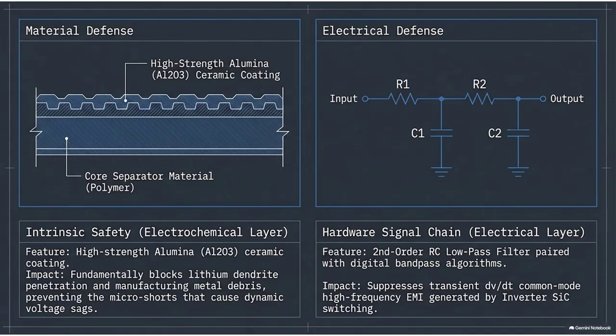But what about the micro shorts? The lithium dendrites and the metal shavings slowly pushing their way through that polymer separator. How do you stop a microscopic spear? You reinforce the polymer with microscopic ceramic armor. Engineers upgrade the standard separator film to something much more advanced. It's a separator inherently coated with a dense layer of high-strength ceramic aluminum oxide, or Al2O3.